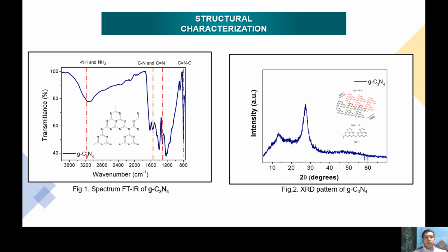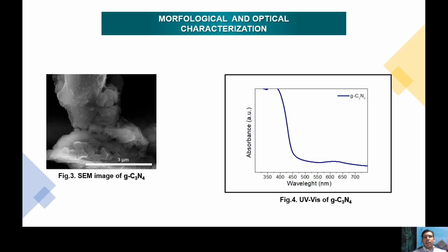As a structural characterization, first, in figure 1, we can see the infrared spectrum of the main functional groups of the C3N4, for the primary and secondary amines, and also we can see the functional groups of the carbon nitrogen bonds, double and single. And also in figure 2, we can see the X-ray diffraction pattern of the C3N4. We can find two main signals. First signal corresponds to plane 100, and this corresponds to repetition of the monomeric molecule. And the second signal corresponds to plane 002, and this corresponds to the stacking sheets of the C3N4.